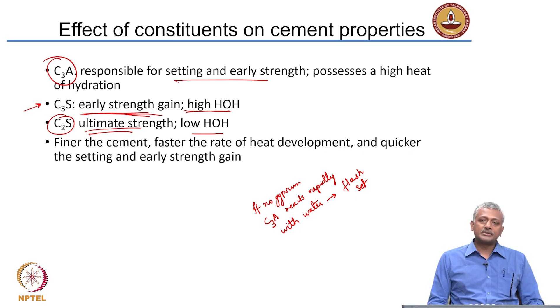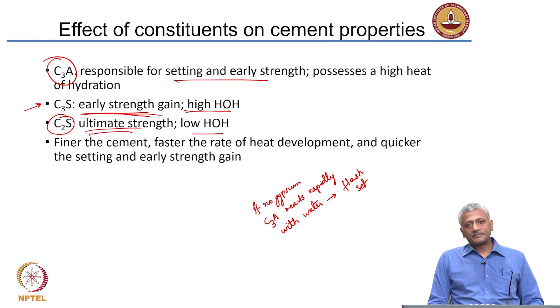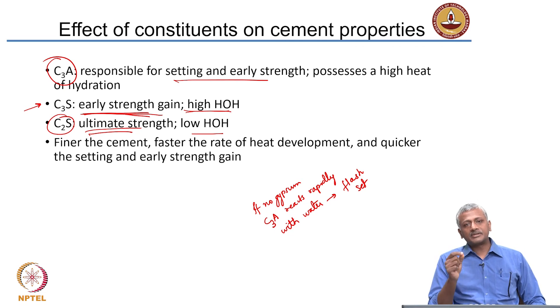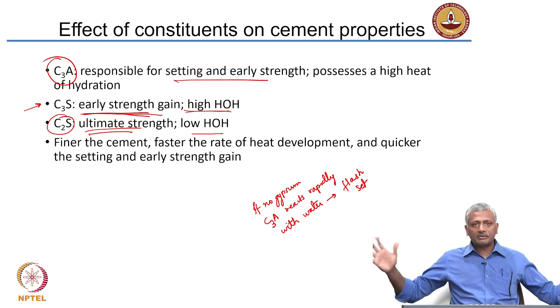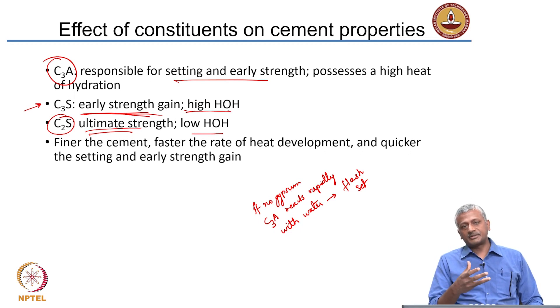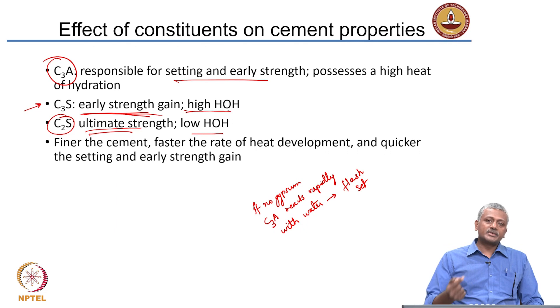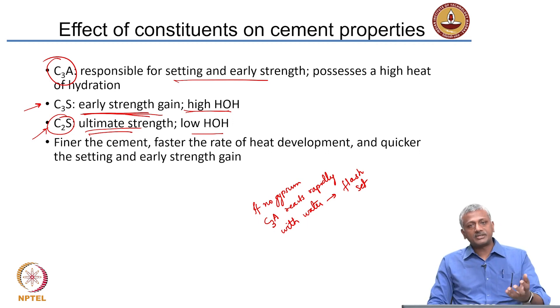For example, if you are constructing a building, the columns will be taking very high loads rapidly, so you will want cement that gains strength rapidly — a C3S-rich cement. In the case of a dam, on the other hand, you have massive concrete, and the heat liberated by cement hydration can be so large that thermal stresses develop because the heat inside does not dissipate easily, leading to cracking. So in such cases, we would like to use cement that produces less heat — cement rich in C2S or alternative strategies.